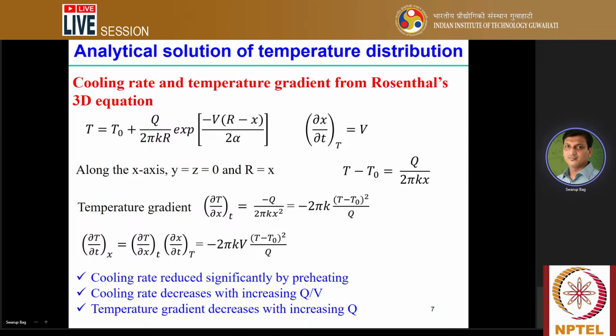So in that case, by modulating the T0 value, we can take care of the preheating effect in this particular equation. Now if T0 is very high, then preheating is there, so T minus T0, the difference, reduces. Once it reduces, the cooling rate reduces if there is a significant amount of preheating, keeping other parameters constant.